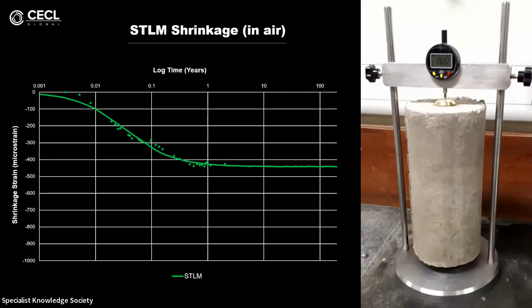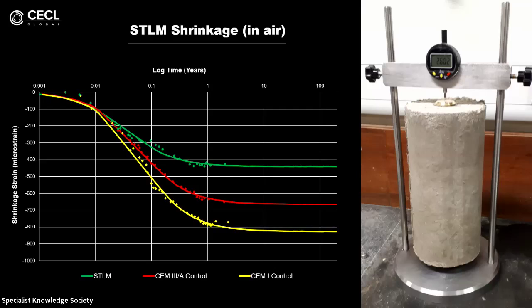So shrinkage is obviously a very important consideration for a monolithic tunnel lining. Formed STLM samples have been monitored for shrinkage for nearly 3 years now, and compared to some conventional cast concrete samples. And we've seen good results when the STLM is compared to these in terms of low shrinkage.